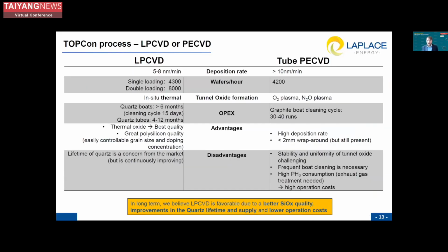When we now compare LPCVD and PECVD a bit more in detail, we can see that on the deposition rate, the PECVD is with over 10 nanometer per minute favorable, while in LPCVD we can reach up to 8 nanometer per minute. When we then look at the wafers per hour, on a single loading, the PECVD is in a similar range with 4,200 versus 4,300 for the LPCVD.